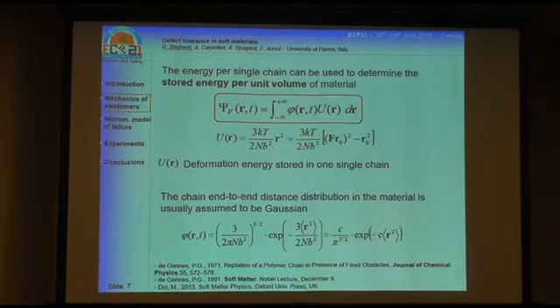So in general, if we want to calculate the mechanical energy for this class of material, we have just to consider all the contributions of all the chains involved in the stretch phenomenon. So we can integrate the energy of one single chain, and we can obtain the energy of the whole volume of material that we are considering. So we have the distribution of the chain length phi and the energy for one single chain. So in practice we are adding up all the contributions by using this expression.